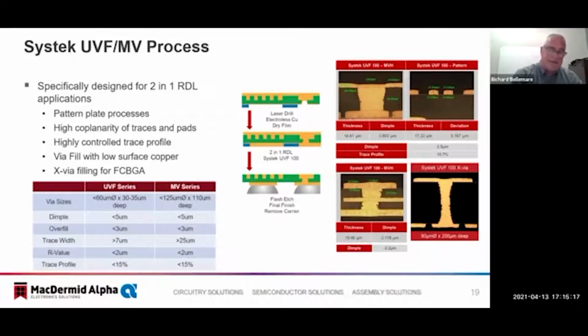The next system that I'd like to talk about is our Systek UVF and MV processes of chemistries. These are electrolytic copper chemistries that are specifically designed for the 2-in-1 plating of RDL structures that consist of microvias, fine lines, and in some cases, laser drilled X-vias. These processes are pattern plate processes that give very high coplanarity of pads and traces, along, again, with highly controlled trace profiles. The main difference between these chemistries is that the UVF was designed for smaller features and the MV series was designed for larger features.